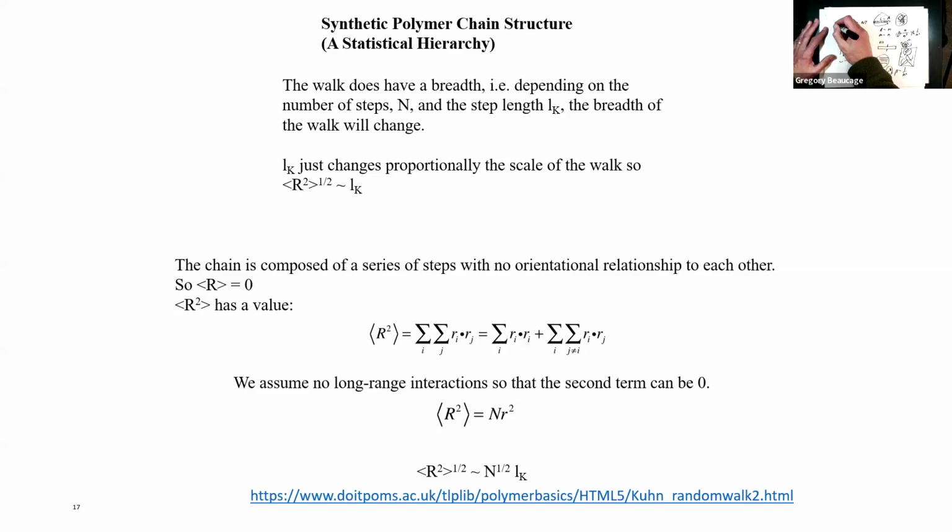Like I showed you a plot of solution viscosity. So that's going to be the viscosity of the solution minus the solvent, normalized by the solvent. When that has a value of 1, generally that's at a concentration of about 1% of polymer. And then you see it'll take off because the chains will start to entangle. It'll go up to the power of about 3. This is the power 1 when you add polymer to a solution. Right, so that's C star. That's the magic place where the polymers start to overlap with each other.